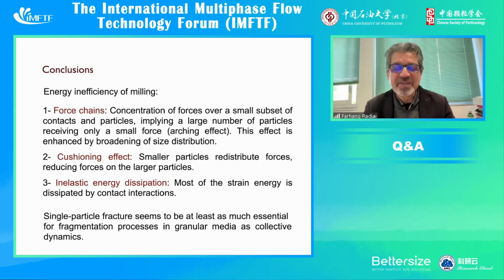This is of course somehow paradoxical, because we are in a state where we expect to have more dissipation and not a larger restitution coefficient. The restitution coefficient quantifies the ratio of the energy after and before the impact. It doesn't mean that there is less dissipation, because we are taking the ratio. So while we are increasing the impact energy, we also have more energy which is not dissipated. So we should see it like this. Dissipation is increasing, but the amount of energy which is not dissipated is increasing as compared to fracture energy.